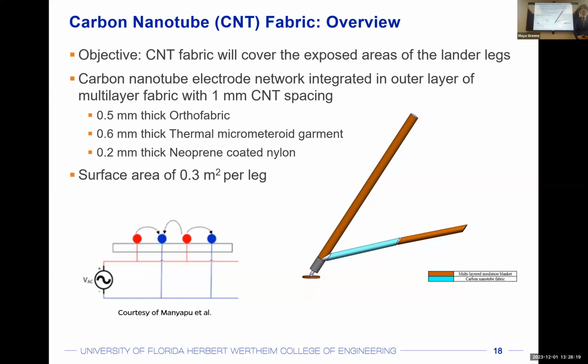This design is derived from a spacesuit dust mitigation system, which conducted experiments on a sample of fabric and found that it was 80 to 96% effective on the dust samples they used.